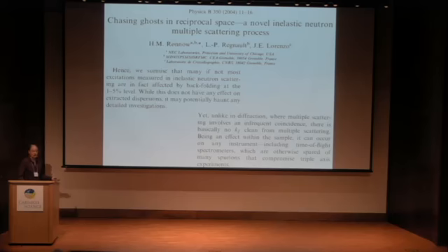And that local mode I showed you is about 3% of the optic mode intensity. And while that does not have any effect on extracted dispersions, it potentially could haunt detailed investigations. And again, this is another important comment he makes. Yet, unlike in diffraction, where multiple scattering involves infrequent coincidence, there is basically no energy that is clean for multiple scattering in large single crystals and neutron scattering. Being an effect within the sample, you'll see it on any instrument, triple axis or time of flight.